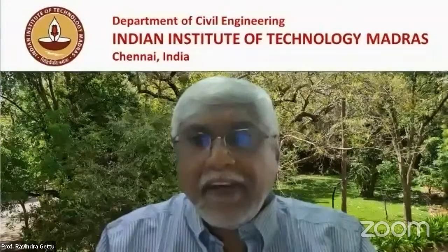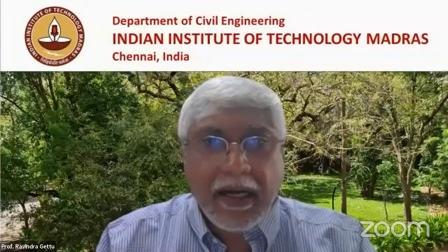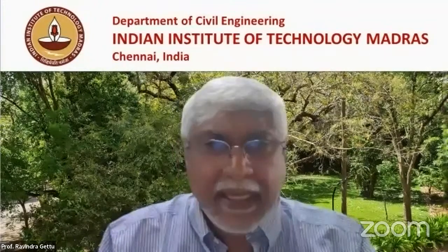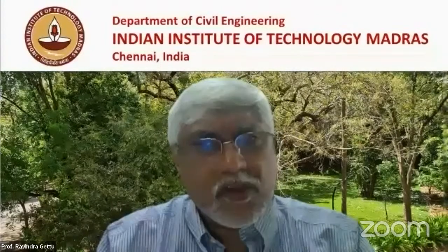So Javed is asking, do we have admixture compatibility complexities? As I have said, Javed, we did not have any problems with LC3 concretes. We could get a slump of 100 mm very easily. So we can help further if somebody has difficulties, but I don't see any issues at all. There are admixtures being particularly developed for LC3, but I don't think that is an issue or a showstopper right now.